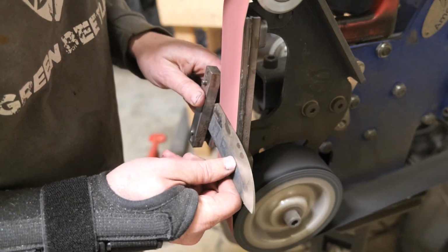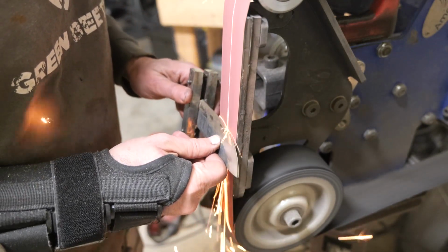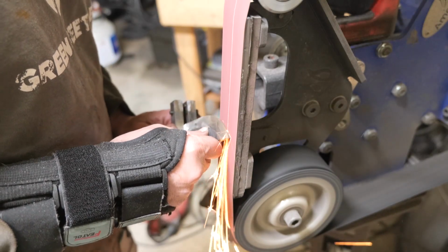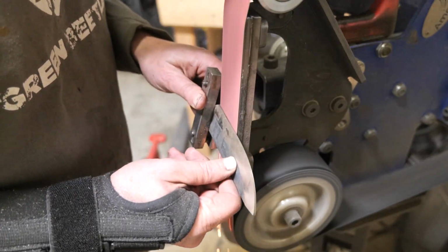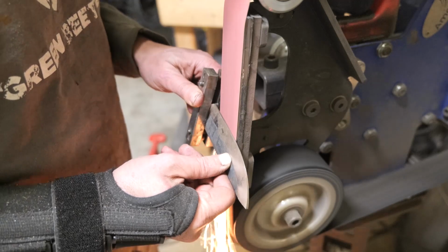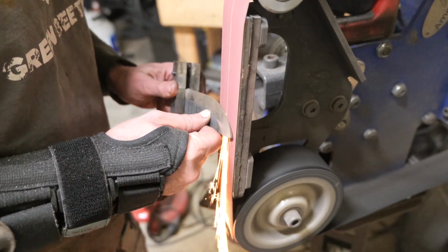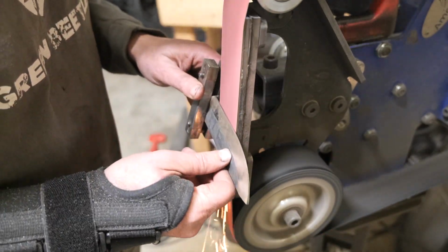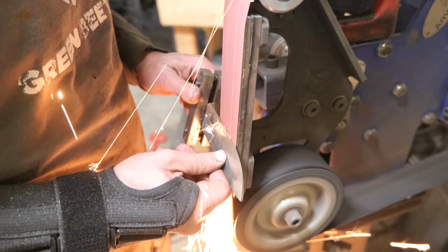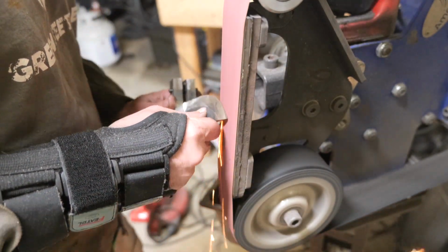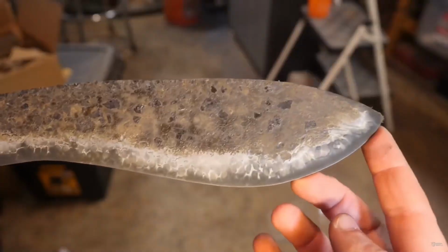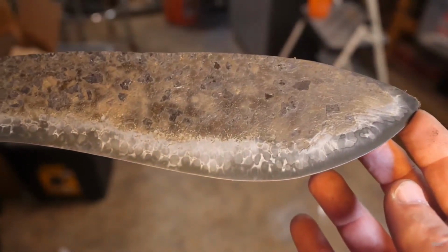We're going to grind in some bevels, and then you'll see me peening the sides of the knife. I saw a few people recommend this as a way to decrease the stresses from the stainless jacket during quench. A major issue with sanmai is the different properties of the core and the jacket material often create a lot of stress during the heat treat that can lead to weld separation, or more commonly the core just splitting down the middle. This is one example of that happening.